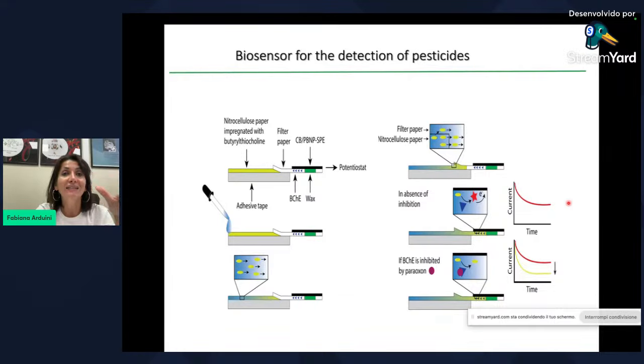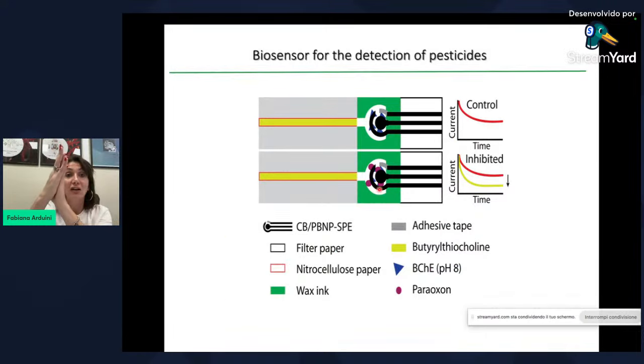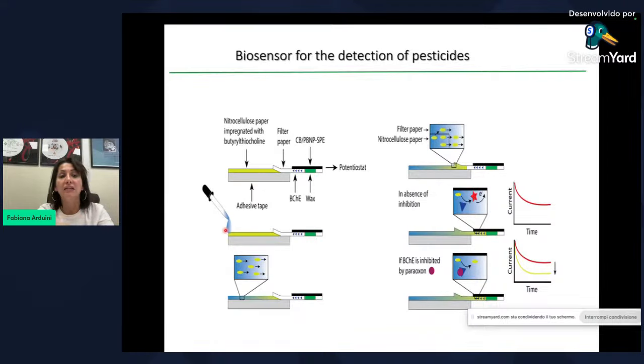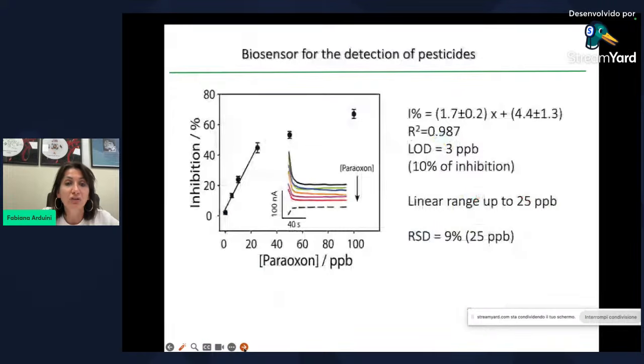When we have to detect the sample, we add the sample close to the electrochemical cell here. We have a reaction; in this case it is irreversible inhibition. And after, we measure the residual enzymatic activity again by adding distilled water in this strip. And we observe a decrease of the response, and the decrease of the response is proportional to the amount of inhibitor present in the sample. In this case, we use paraoxon as a model, obtaining a detection limit of 3 ppb and a linear range up to 25 ppb.